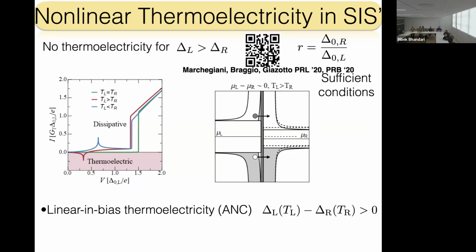Okay, now let's try to get which is the sufficient condition. The first point is that you see, I am even linear because I'm just a little bit shifting. So I'm linear in the voltage, but I'm not linear in the temperature. If I repeat the argument and I put the temperature big, identical here, again, there is a full cancellation. First. Second, different gap, as I said. Another important point is, independently of the structure of the density of states here, it's not so important. What is really important is the density of states on the cold side, okay? So monotonically decreasing density of states on the cold side. And last ingredient, the density of states shifts with the chemical potential. And these are all the ingredients.